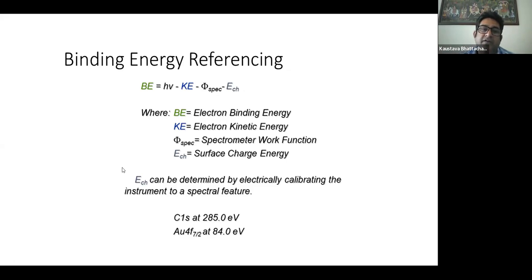For that, we usually always take the carbon 1s as the internal calibrating agent. So we get the 1s at almost 284.5 electron volt. We need to calibrate that. Initially, we need to calibrate the instrument with either gold, copper, or silver, any one of the two. And once we know the instrument is perfectly calibrated, then we can substantiate that the carbon 1s will have a value of 284.5 eV. And now if that particular carbon 1s is at a higher value than 284.5 eV, we can understand the surface charge from that, and we need to reduce that surface charge to get the exact binding energy for the elements concerned in the system.